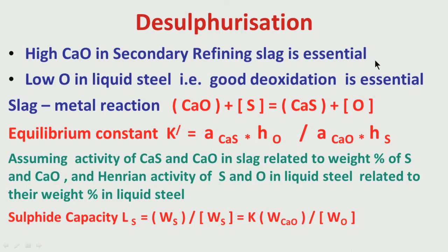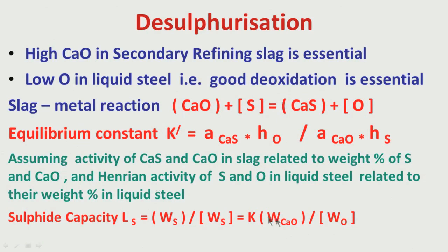So, for all secondary refining, again I am repeating, the first activity is deoxidation. Once we achieve good deoxidation, that means the solubility of oxygen in liquid steel is brought down to say less than 5 ppm, then desulphurization will be very effective. I think it is very clear to you now why deoxidation is necessary first and then good desulphurization is possible, and I am giving you a concept of sulphide capacity of the slag. That means the slag must have a very good amount of CaO, then only it can hold on to the sulphur in the slag. That means the wt% of sulphur in the slag in the form of calcium sulphide will be more when you have more calcium oxide. So, the sulphide capacity of the slag is very important.